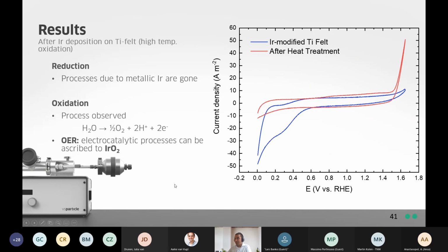However, if we compare this to the material that was calcined, so again, here we have the CV plot, and now the plot in red is the calcined material. You see that all the reductive steps or the reduction steps are gone, and they've been replaced with a single oxidation step, which is attributed to the oxidation of water to form oxygen, which confirms that we've prepared an oxygen evolution reaction electrocatalyst. And this again confirms that we've prepared iridium oxide nanoparticles on these titanium felts after we've done the calcination step.